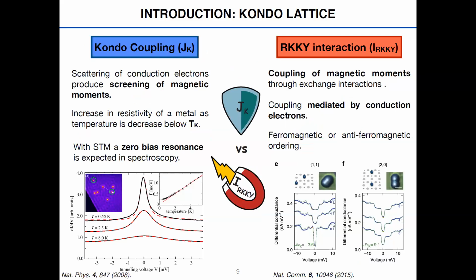Both the Kondo coupling and the RKKY interaction are many body effects. They involve a magnetic moment interacting with the conduction electrons of a metal. In the case of the Kondo effect, this effect emerges when the conduction electrons are screening this magnetic moment. This screening is produced by a scattering and spin flip process in which the spin of the magnetic moment is flipping between the two possible directions.